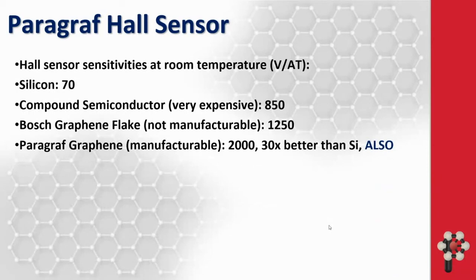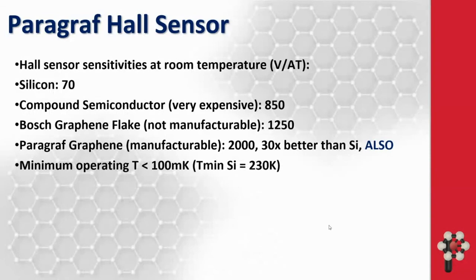Ours is 2000. It's manufacturable, so it's 30 times better than silicon, and also it operates at really low temperatures, down to below 100 millikelvin. The minimum of silicon is 230 K, so you can't do cryogenic work with the silicon.